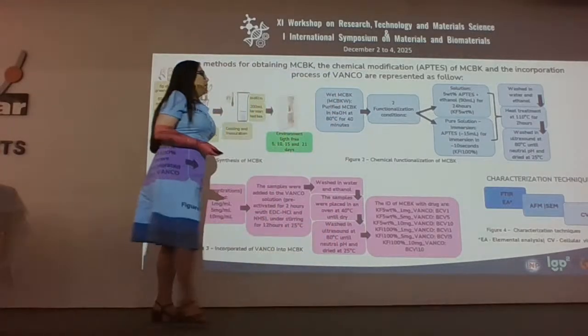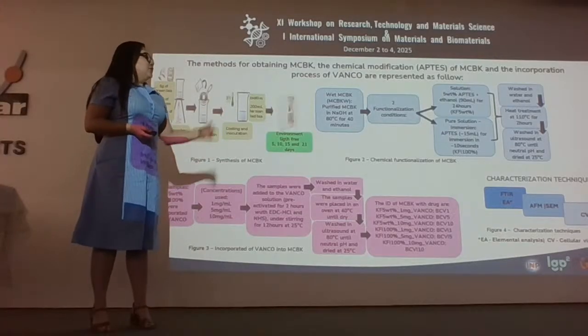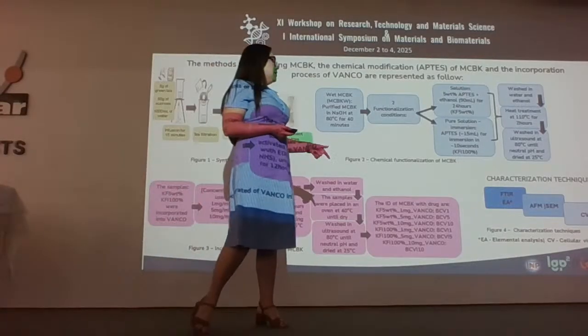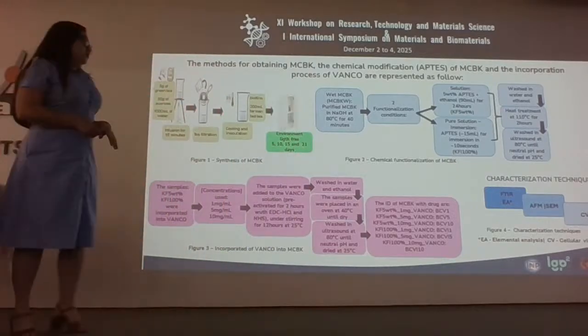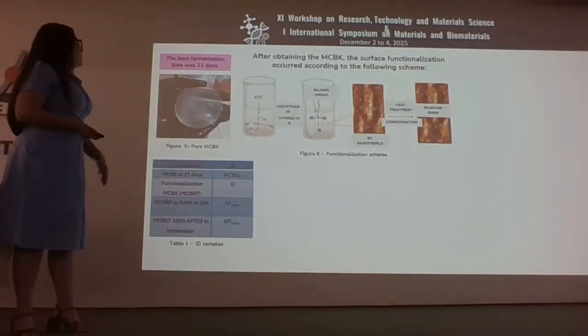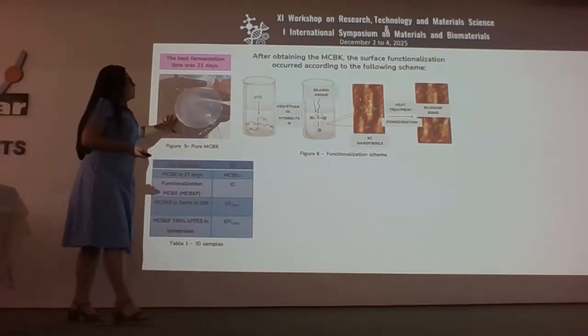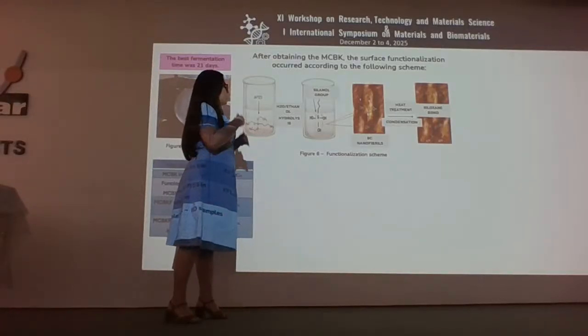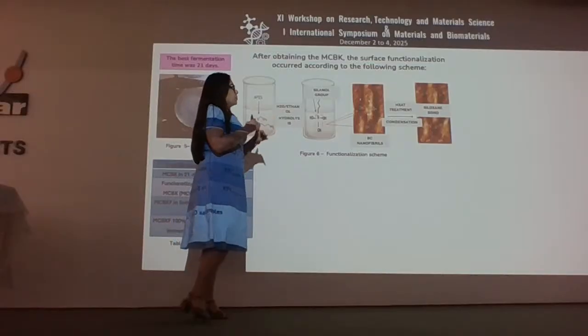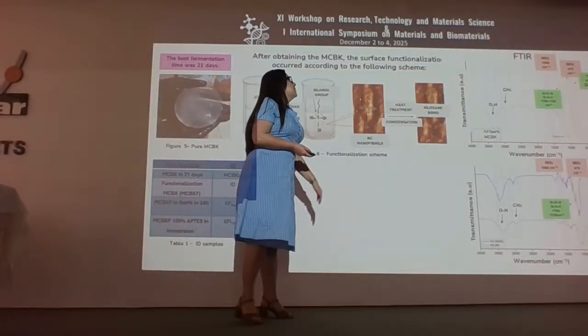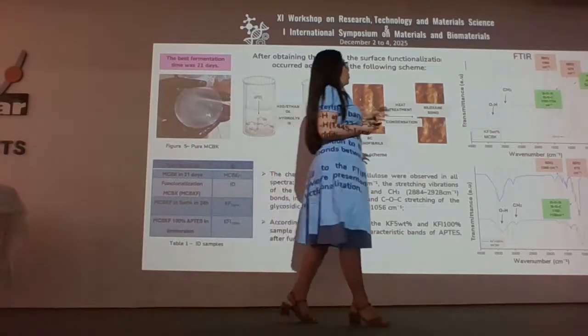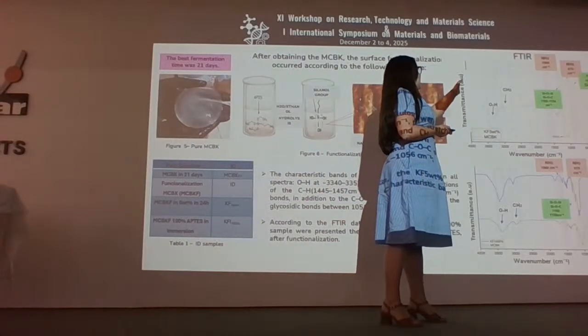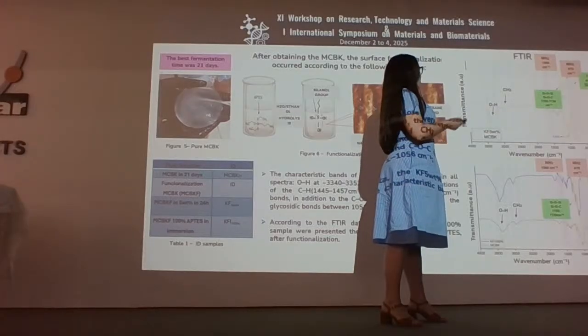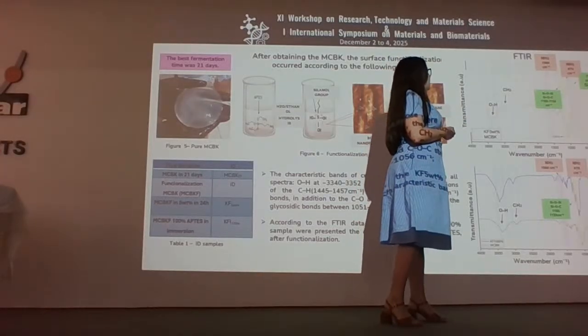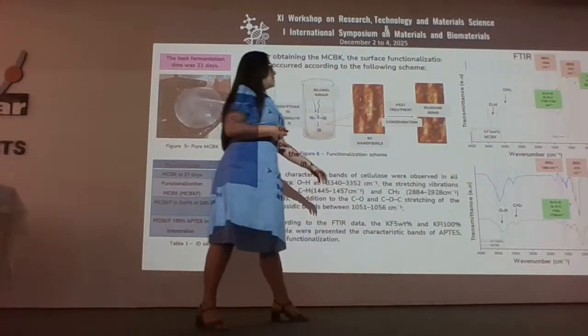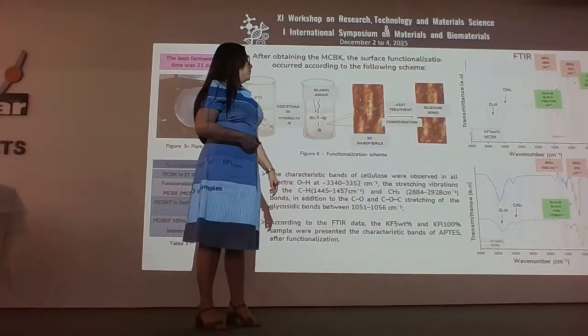So in the characterization techniques, I use FTIR, elemental analysis, AFM, and cell viability, and others, but today's presentation is focused on some of them. This can represent the reaction occurring during the chemical modification. To confirm this, introducing the special groups in the surface of the MCBK, the FTIR spectra confirm the main bands, in special amino groups and silanol groups, in the introduction in the surface in both conditions of the chemical modification.